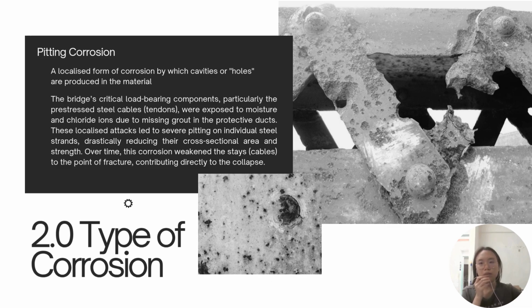The bridge collapsed because of pitting corrosion. Pitting corrosion refers to a localized form of corrosion by which small cavities or small holes are produced in the material or on the surface of the metal. The bridge's main component, the steel cables that encase the bridge's concrete, were exposed to moisture and chloride ions due to missing grout in the protective ducts. This localized attack led to severe pitting on individual steel strands, drastically reducing their cross-sectional area and strength. Over time, this corrosion weakened the cables to the point of fracture, contributing directly to the collapse.